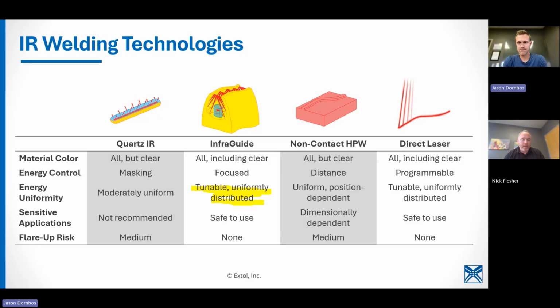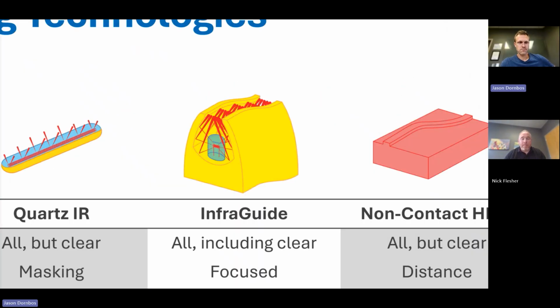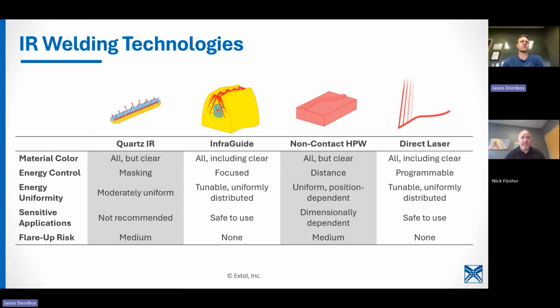And so, we say there's a medium risk because we have mitigated that before with things like nitrogen, or the parts will self-extinguish. The part actually isn't burning. It's what's coming off while you're emitting. InfraGuide has none. And the reason that we want to park on this for just a moment is we actually cool the tool with air that pushes all of those fumes away from the weld rib and away from the emitter. So just kind of keep that in mind. And it's not all resins.